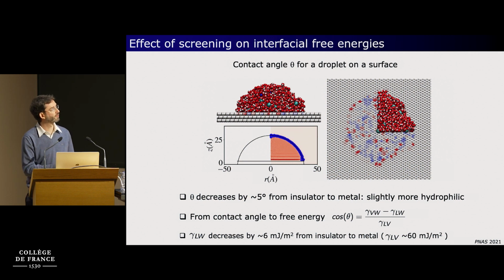To start, I would like to consider contact angle measurements, or at least measurements in our simulations, of how the contact angle of a drop of electrolyte changes when you change the metallic character of your solid. And so here we have a drop of a liquid. We let it evolve for some time. We can measure the average shape. Here you have a top view where only a fraction of the liquid is shown, so that you can see that the local charge on the metal is associated with the local structure of the liquid, which you don't see, but you can guess. And so depending on the orientation of water and the presence of ions really in contact with the liquid, you have different local charges in the metallic case.